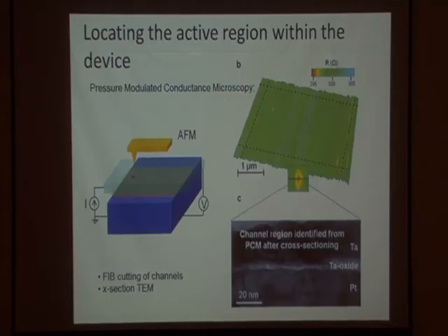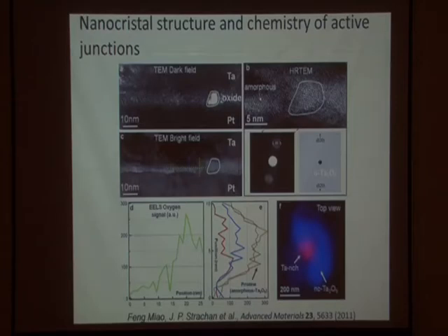So you find the switching center and you cut, then you prepare your TEM sample, and that's what you do. This is what we found. It's a relatively complex graph, and this was published in Advanced Materials last year. It was a lot of work, but to make a very long story short, what we learned from this experiment is illustrated better by a different type of experiment.